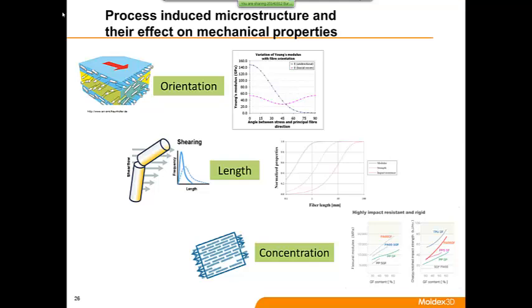We not only care about the orientation, we also care about the fiber length. With the increasing of the fiber length, fiber retention becomes more and more important, and also with the increasing load of the fiber. Right now, a typical fiber for nylon, you can pretty much go to 55% fill. That's a common case right now. So on this really highly concentrated system, can you also always have a really homogeneous distribution of your fiber?